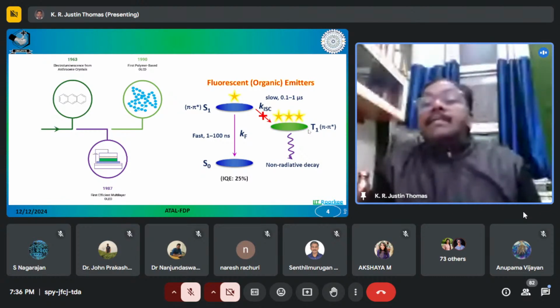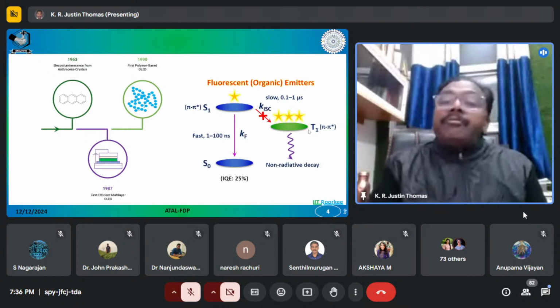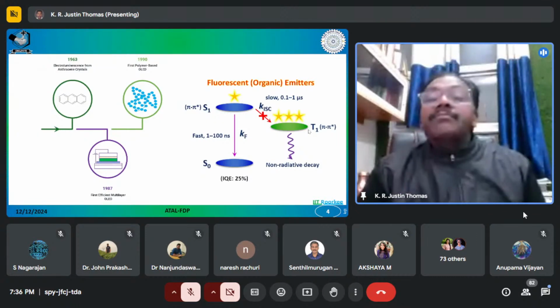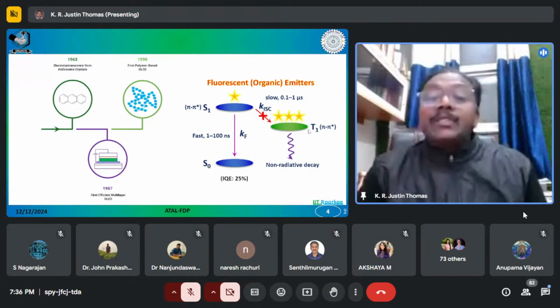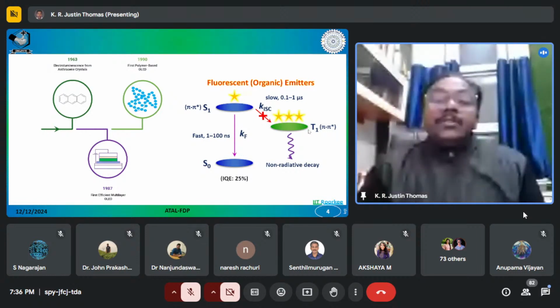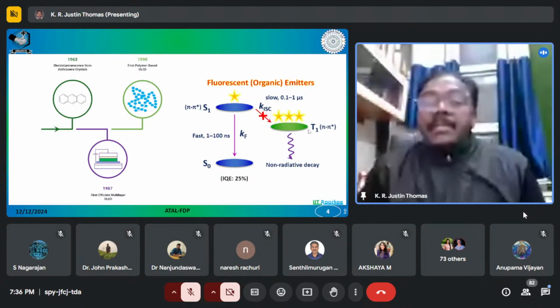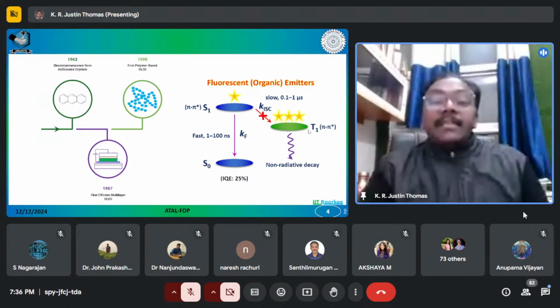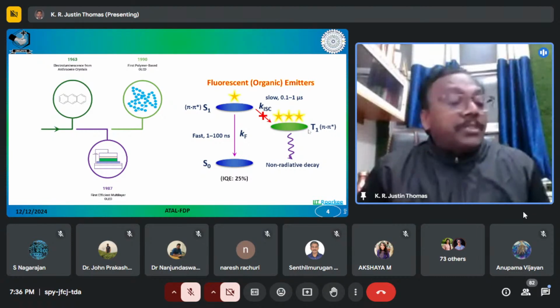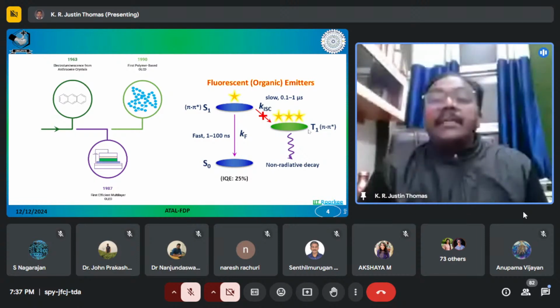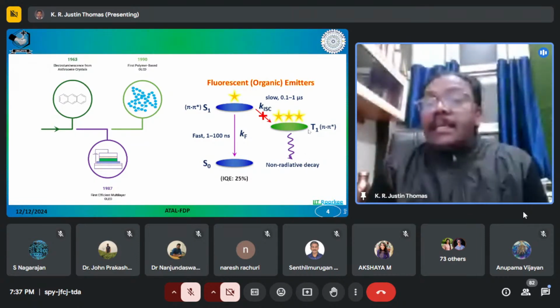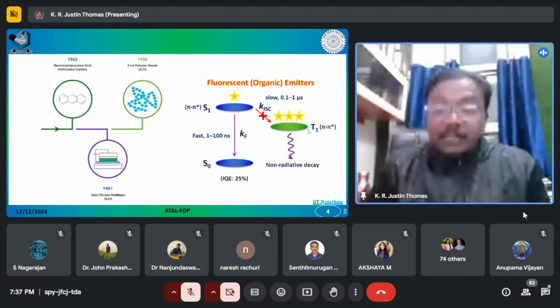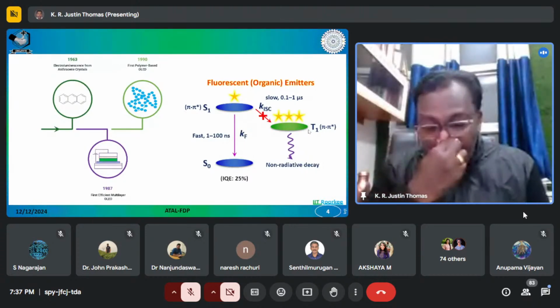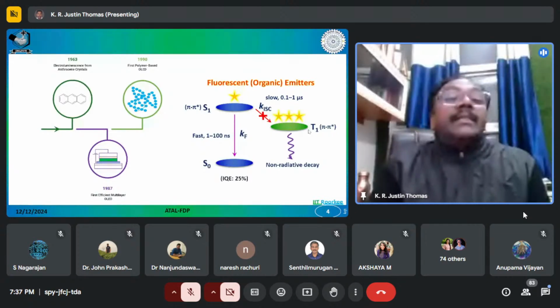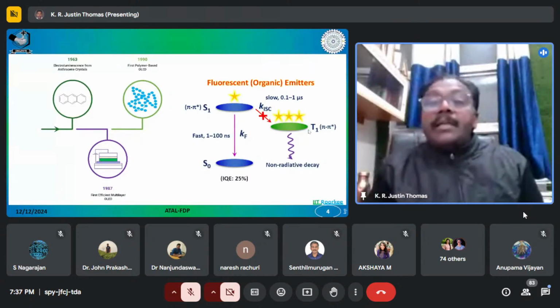So number one is that the singlet excited state of the organic emitter is far away from the triplet excited state of the organic emitter. So the gap between the S1 and T1 is generally large. Okay, so that is the first problem. And second is that you have a spin crossover. You have a singlet state to triplet state. So as per the rules that govern electronic transitions, delta S has to be 0. Here there is a change in the spin when there is a transition taking place from singlet to triplet state. So that means that the organic emitters cannot easily undergo an intersystem crossing. So you cannot use the triplet state of the organic emitters in the LED emission. That is the important problem with the organic emitters.